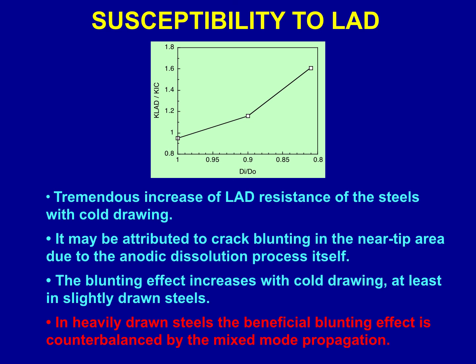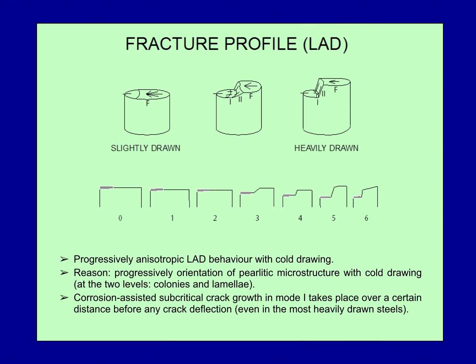It may be attributed to crack blunting in the near tip area due to the anodic dissolution process itself. The blunting effect increases with cold drawing, at least in slightly drawn steels. In heavily drawn steels, the beneficial blunting effect is counterbalanced by the mixed mode propagation. With regard to the analysis of the fracture profile and localized anodic dissolution, we have shown this picture before in 3D and in profiles 2D.